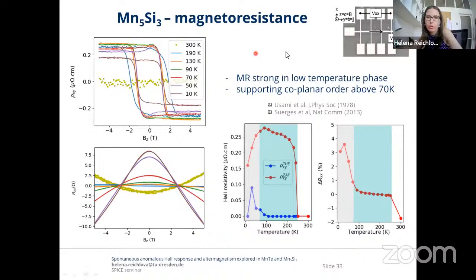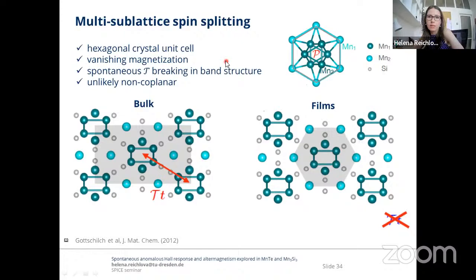We also measure the longitudinal signal, the magnetoresistance. Unlike the anomalous Hall effect, which is present in the full temperature range when the sample is magnetically ordered, the magnetoresistance is negative and present only in the low temperature magnetic phase, the non-collinear low temperature phase, and is basically absent in the high temperature magnetic phase, as can be illustrated here. And this further supports the coplanar order in the high temperature magnetically ordered phase, again consistent with the previous literature. So let me now explain where we think that the signal actually comes from.